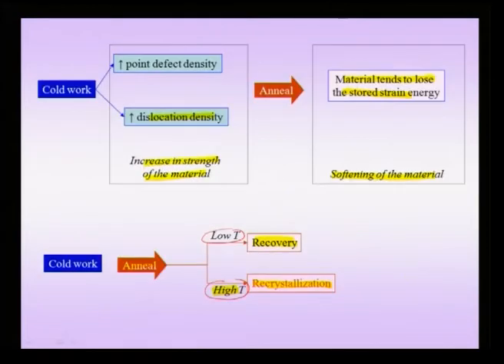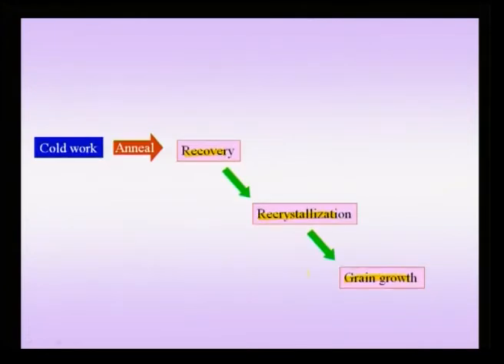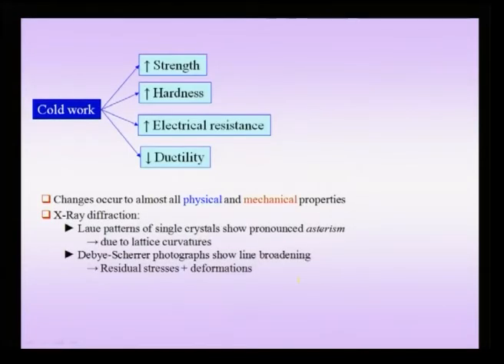In the case of even high temperatures, there would be recovery, but since the dominant process is recrystallization, we have written it as recrystallization. So, in the whole process, we will see that the physical properties of the material change, and in fact physical and electrical properties etc. change, and you would notice that the material is changing its properties due to a change in microstructure. And now, as we pointed out, there is actually no phase transformation involved in these processes, it is actually what you might call microstructural transformation.